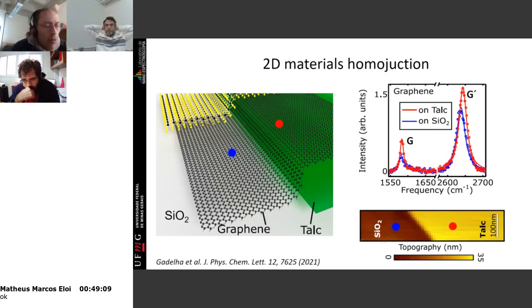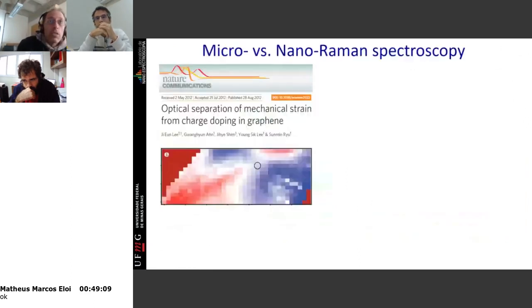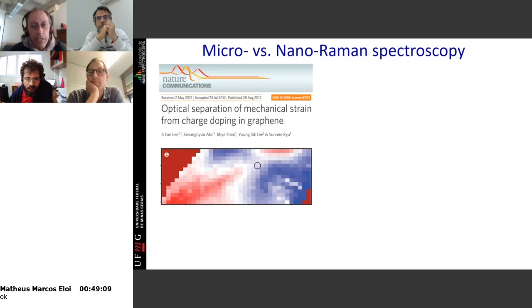So Caio, you're very fair question, because I didn't explain a very fundamental aspect, which is how do you know if you are looking at strain or doping or both? You are right that both strain and doping change the frequency of these peaks, the frequency, the intensity, etc. But what was established by those Korean guys, this work here, what they showed was the following: if you have a graphene system, and you measure different locations with different doping, the frequency of the two peaks, they change with a given slope, if you plot the frequency of one with respect to the frequency of the other.